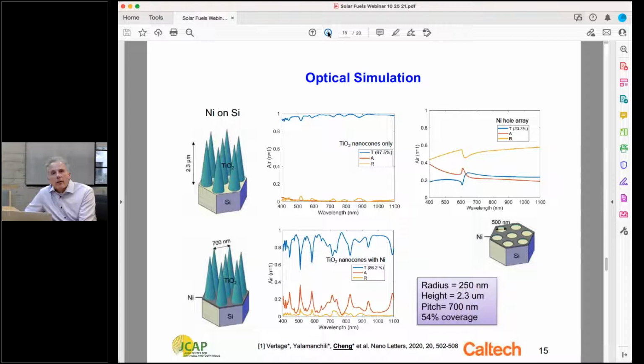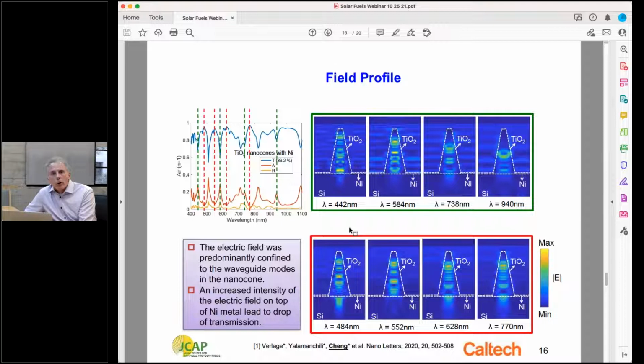Effectively, these waveguides tailor the light coupling into the photoelectrode. This shows what the optical modes look like. You can see here, across the visible spectrum, the evidence of transmission in electromagnetic simulations through these optical dielectric nanocones that tailor optical transmission, shown at each of these resonant transmission points. There are multiple resonances in a cone-like structure, each resonance happening at a different cross-section of the cone, giving rise to essentially a broadband resonant transmission.